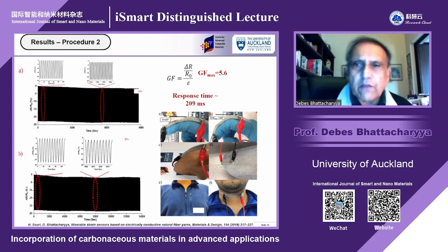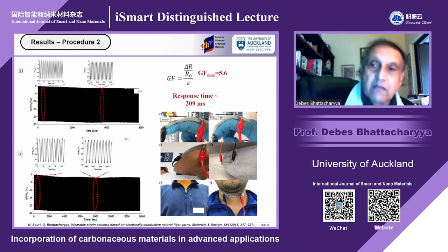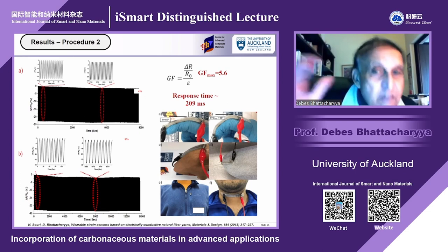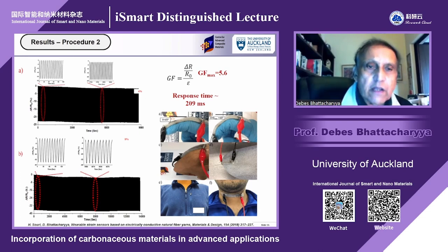Gauge factor was not that high, but not bad, 5.6 or so. People, when they get 10, they said, we have got very high gauge factors. We got extremely high gauge factors. I'll show you later. But it is very stable. You can see from the left-hand side, results are stable.